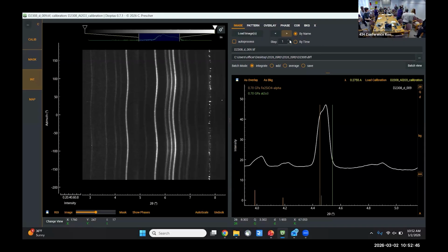But when we deform the mineral, so we're under high pressure, we've squished it, and now we're driving our top and bottom rams to deform it in one direction. These planes here, they're going to get smaller in this direction. So these planes will be more crunched together than the planes in this direction because we're not pushing the crystallographic planes together in this direction, but we are in this direction. So what happens is these ones will actually get a little bit wider that are perpendicular. So it'll diffract out here.